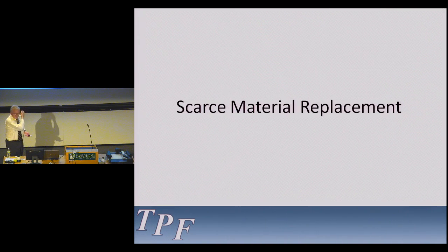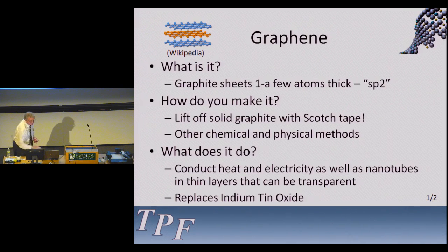So let's talk about scarce material replacement. Graphene's the other interesting form of graphite that's been developed in the last few years. And this is basically, instead of taking your graphite layers and rolling them up into carbon nanotubes, you just strip them off one at a time. So you can produce relatively large flakes, and you can actually do this. If you take a single crystal of graphite and put Scotch tape on it, you can actually rip single layers off. That's not a good production process.